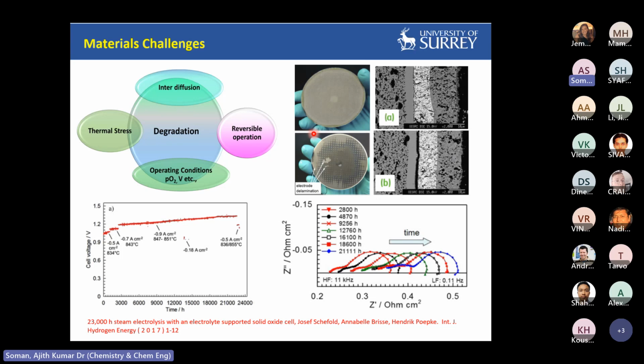That is the degradation. We are critically looking into reducing the degradation effect, because the cell operates under high temperature. It undergoes a lot of thermal stress, and there could be a lot of interdiffusion of elements between the layers. And if we are interested in reversible operation, it also increases the degradation rate. Of course, the operating parameters, because we are changing the voltage, and the different partial pressure will also affect the cell performance. So we are looking into addressing the degradation issue, because this particular problem is so challenging for commercializing the cell.